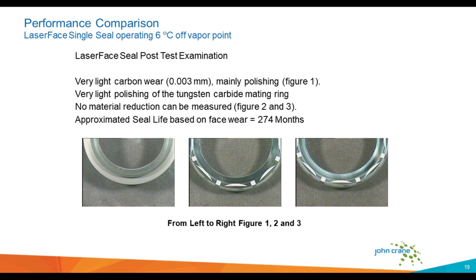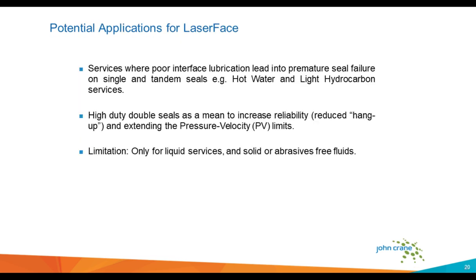In the laser face post-test examination, we noticed that there was very light carbon wear, about 0.003 millimeters, almost negligible, mainly polishing. Very light polishing of the tungsten carbide mating ring. No material reduction can be measured on both. So approximate seal life based on face wear was 274 months.